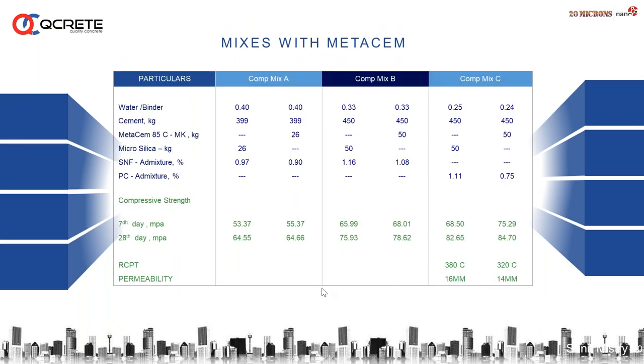The second series you can see here, this is the straight away comparison. I have not mentioned the aggregates part and all here, just wanted to convey the at par result, especially for the compressive strength. You can see here, keeping the water, in one trial we did a water cement ratio on a higher side of 0.4. The second, we did a trial keeping the water cement ratio of 0.33 and the cement content of 450, and see the results. More than a 70 grade concrete is achievable here. On a 28 days result, you can see like 75 to 78, and it is a comparison between the Metakaolin and the silica fume.